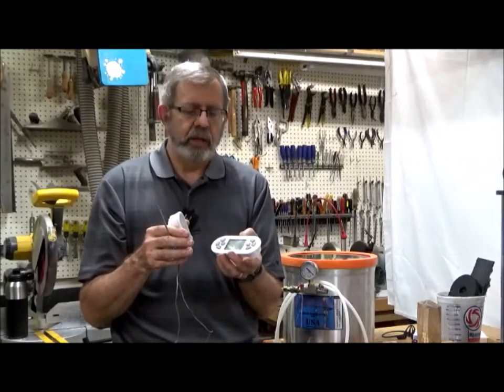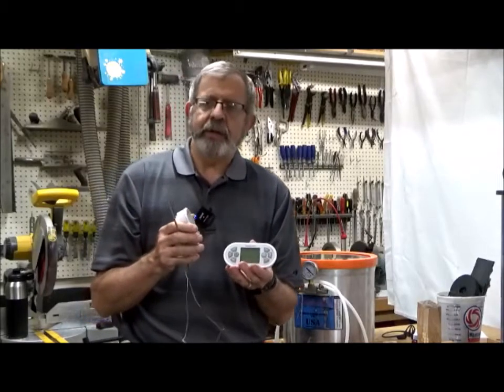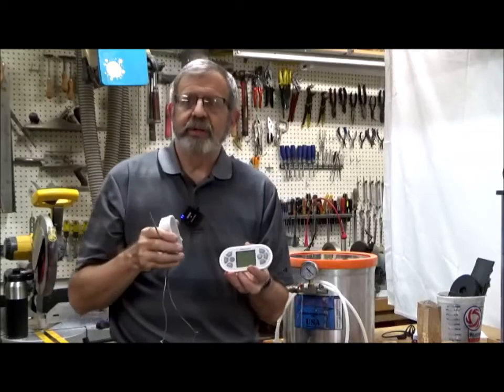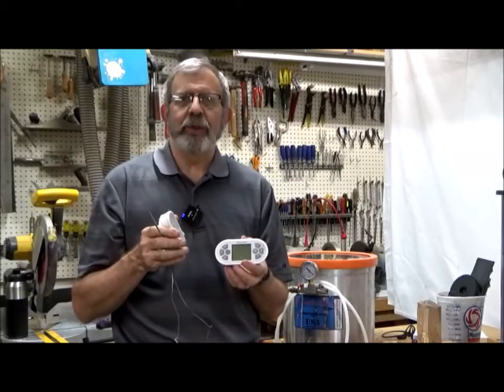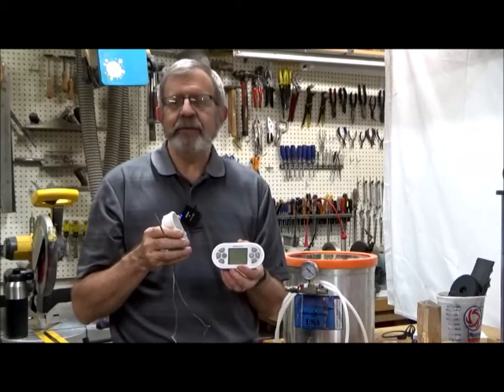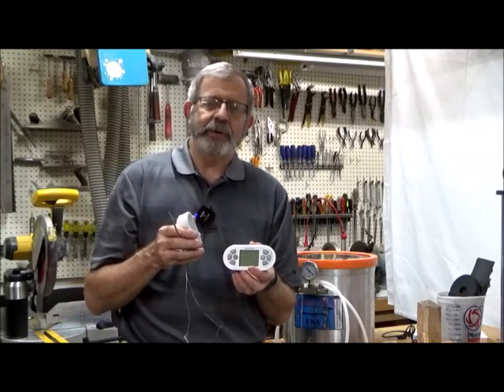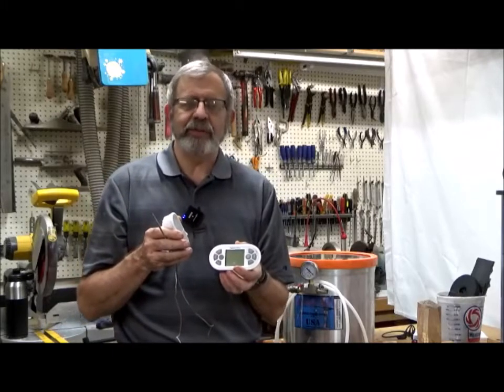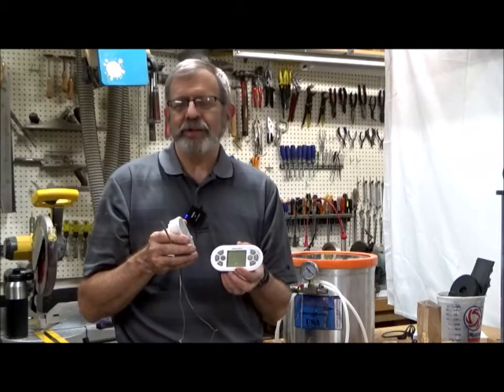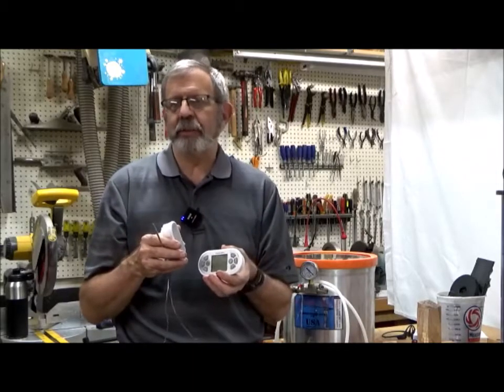So there are some people on the internet that wrap their pieces in aluminum foil before they put them in the oven. I have found that that does not help retain the resin in the wood, and it makes it a terrible mess to clean up, because the foil is all stuck to the blanks, and you end up having to sand it off.